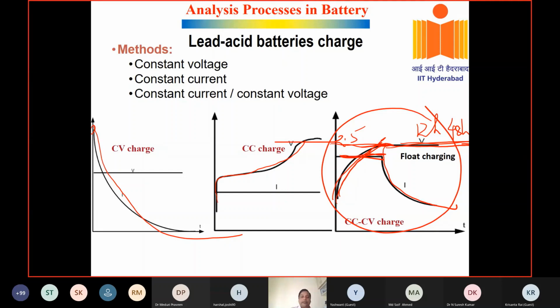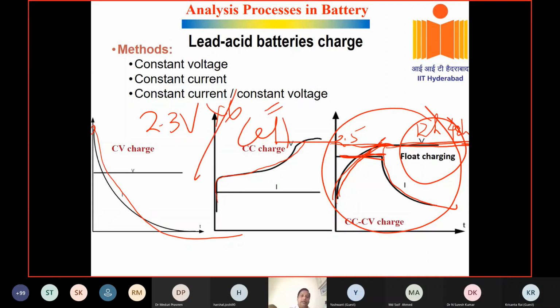So these are the three different ways of charging: constant voltage, constant current, and constant current followed by constant voltage. Generally, your inverters are charged at something like 2.3 volt per cell into 6, which is 13.8, so it's always float at 13.2 volt. So a very small amount of current will be passing into the cell.